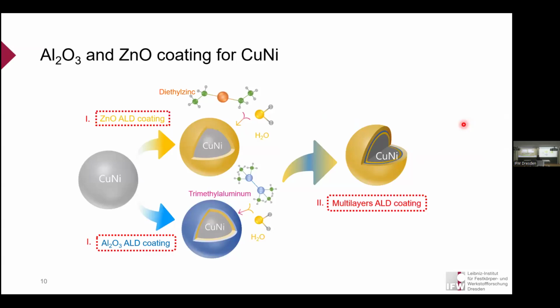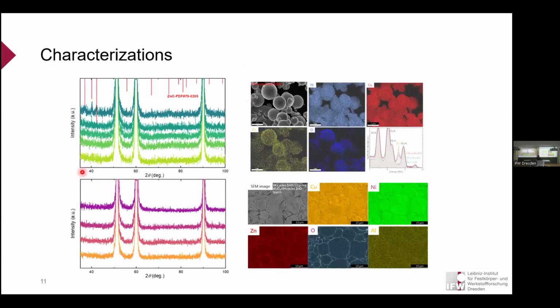So with this technology in hand, we're starting from the metallic material. The most famous metallic thermoelectric material, of course, is copper nickel. And we take this material and coat it using atomic layer deposition with either zinc oxide or aluminum oxide. We also do multiple coatings, layered zinc oxide and aluminum oxide, to tune the coating properties. We can see the coating of zinc oxide, but not aluminum oxide, because aluminum oxide is an amorphous material.